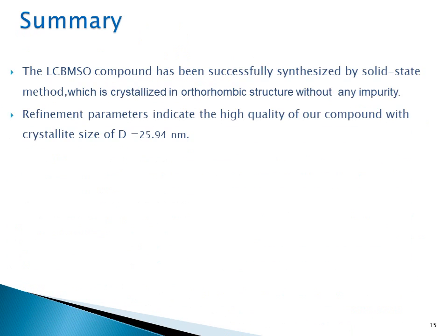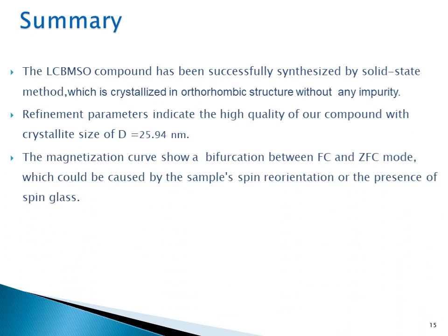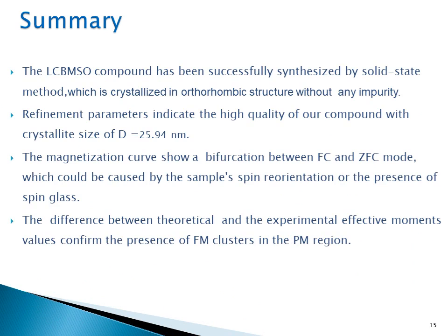In summary, the LCBMSO compound has been successfully prepared by the solid-state method. Refinement parameters indicate the high quality of our compound. Magnetization curves show a divergence between FC and ZFC modes, which could be caused by simple spin reorientation or the presence of spin glass nature. The difference between theoretical and experimental effective moment values confirms the presence of ferromagnetic clusters in the paramagnetic region.